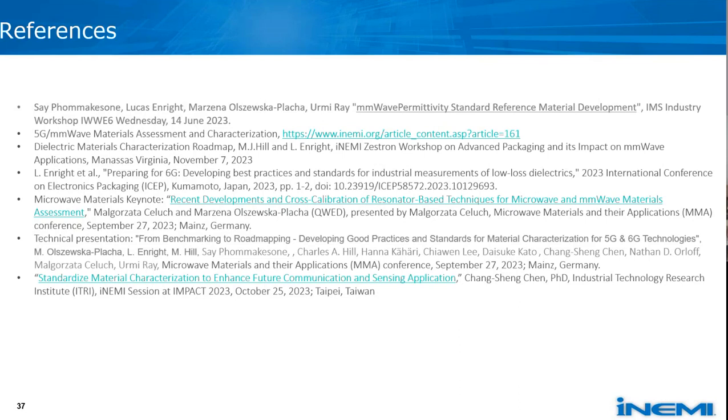Sure, yeah. We actually spent quite a bit of time on this question of isotropy. One of the other materials that obviously bubbles up to mind is sapphire. But we really didn't want to start out developing something that had significant anisotropic behavior, because we wanted to be able to use the standard in both methods that provide permittivity out of plane and in plane, so that you could have one standard that satisfied both. So we ruled out sapphire pretty quickly, even though there are a lot of properties there that would make it very nice.